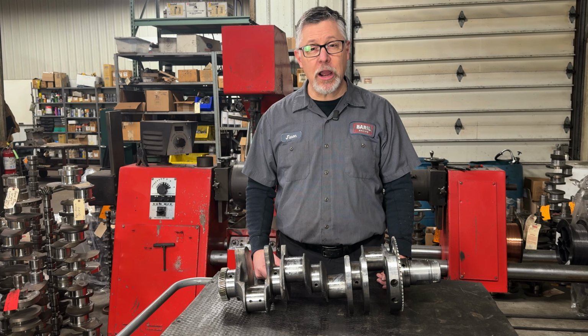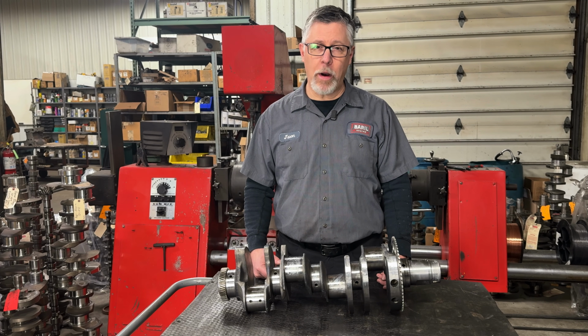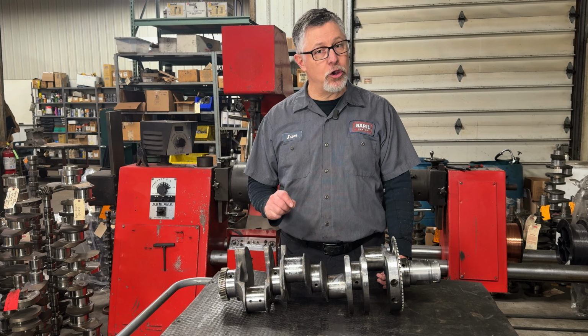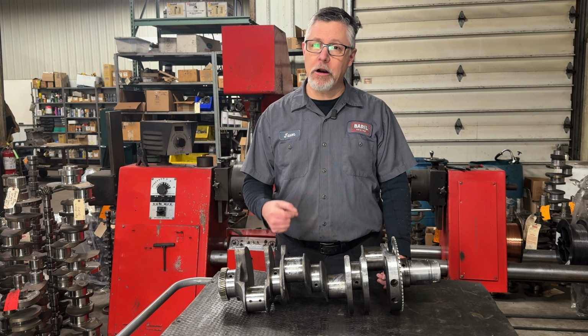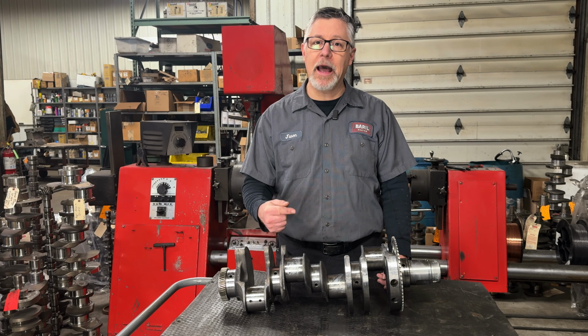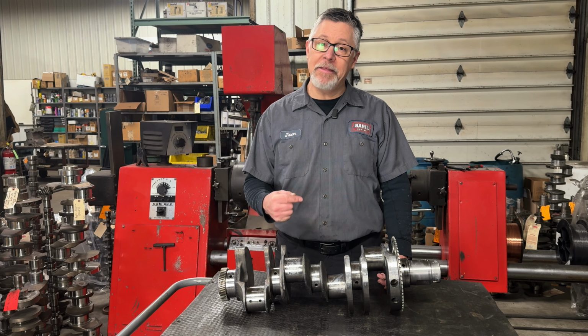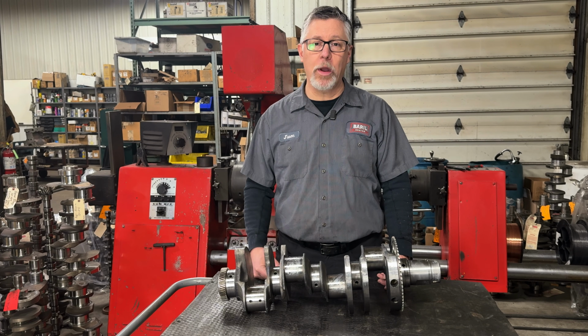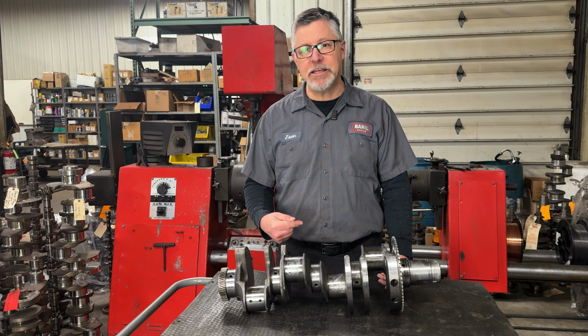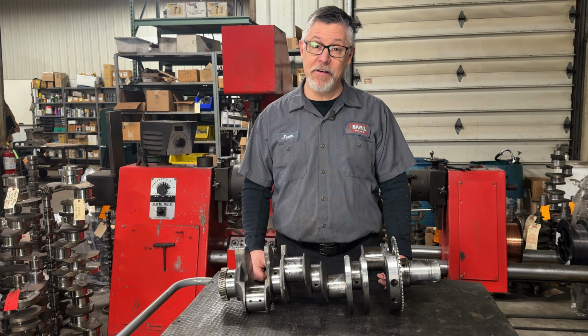The other thing that we shy away from is repairing cracks in crankshafts. While we could grind out a crack, it's our experience that cracks go well beyond what we can visibly see. And in that circumstance, once we've filled the weld back in, reground that crankshaft, there's a reasonable chance it will continue to crack, get worse, and eventually break.